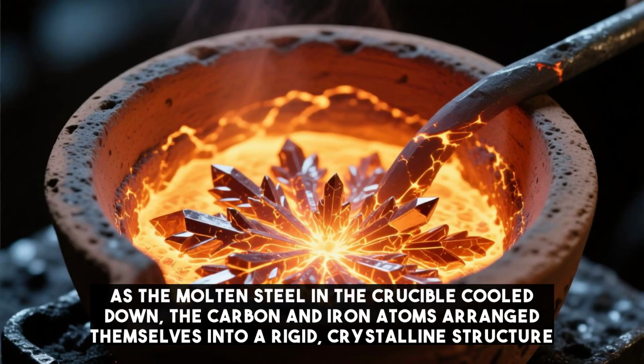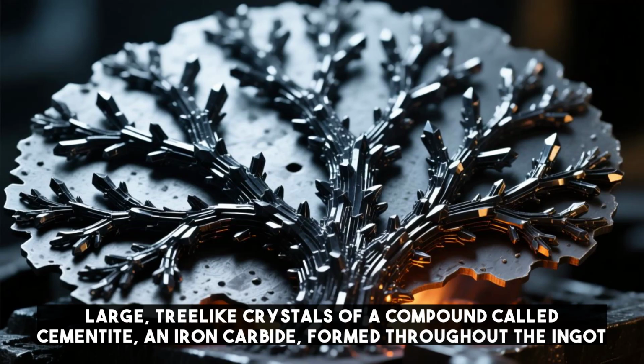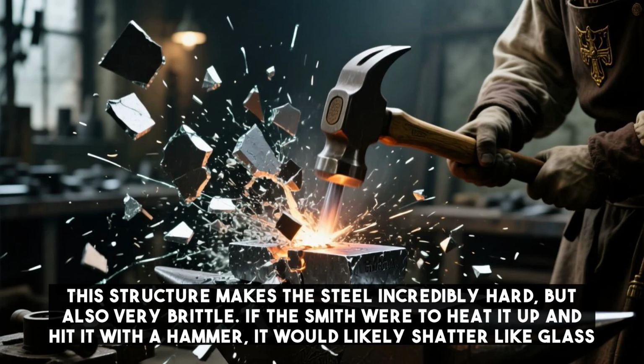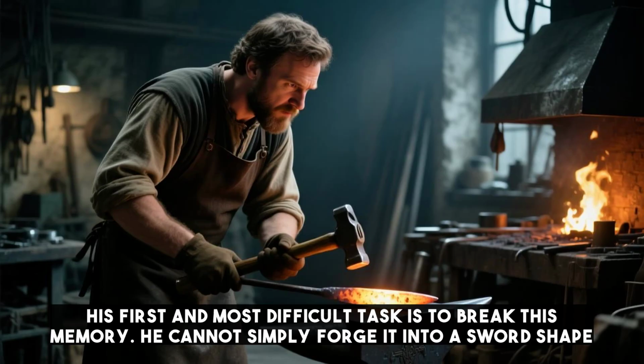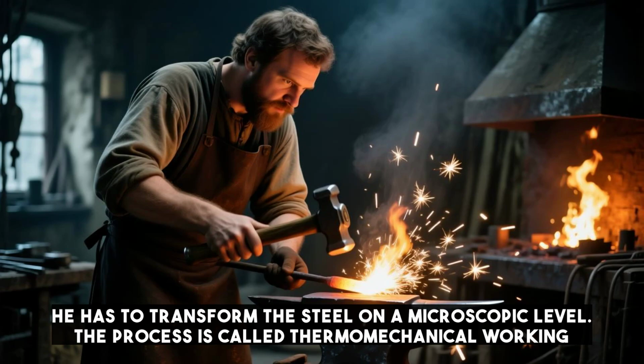As the molten steel in the crucible cooled down, the carbon and iron atoms arranged themselves into a rigid, crystalline structure. Large, tree-like crystals of a compound called cementite, an iron carbide, formed throughout the ingot. This structure makes the steel incredibly hard, but also very brittle. If the smith were to heat it up and hit it with a hammer, it would likely shatter like glass. His first and most difficult task is to break this memory. He cannot simply forge it into a sword shape. He has to transform the steel on a microscopic level.